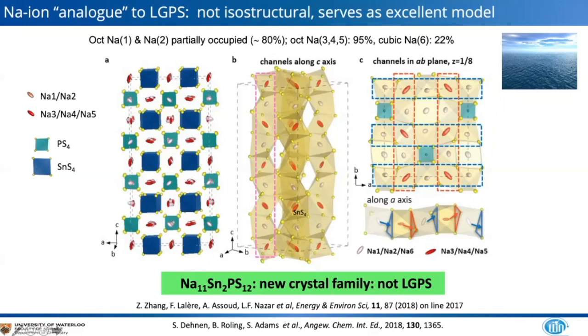There's also an additional site, which we call the sodium 6 site, which is a cubic site. It's not so important. So the point here is that the sodium 1 and sodium 2 positions are partly occupied. These are the ones depicted in a light rose color, whereas the other three sodium sites in the lattice are about 95% occupied. So we have an occupied, partially occupied, occupied, partially occupied, alternating motif in the lattice, which gives rise to good conductivity, in part because we lower the energy for defect formation because of these partial vacancies. The structure was reported by us in EES in 2018, and at about the same time, or very shortly thereafter, by Stefanie Dehnen and Bernd Roling's group.